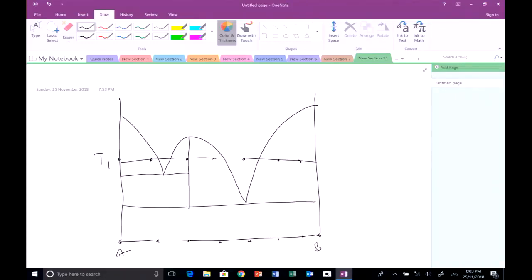And if we take these as compositions 1, 2, 3, 4, 5, 6, 7, 8, composition 1 is just solid state A. Okay, that's not going to be very exciting. Maybe it'll densify, maybe it won't, who knows. Composition 2 is going to have a lot of liquid in it, isn't it? So it's lost its shape. We press the pellet and it spread out. Not too good. Composition 3, on the other hand, we had a big chemical reaction, and the pellet fell apart into a powder, but it didn't melt.